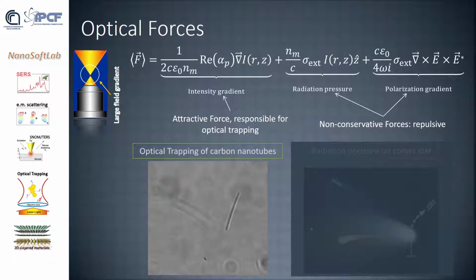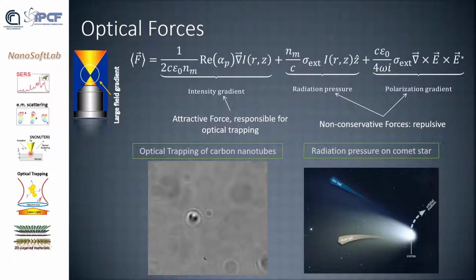Here you see some carbon nanotubes that, when the laser is off, fluctuate normally, and when the laser is on, they are trapped. If this intensity gradient force is strong enough, we will trap the particle. Otherwise, if the radiation pressure is stronger, we see a comet effect in which particles are pushed away from the focus.